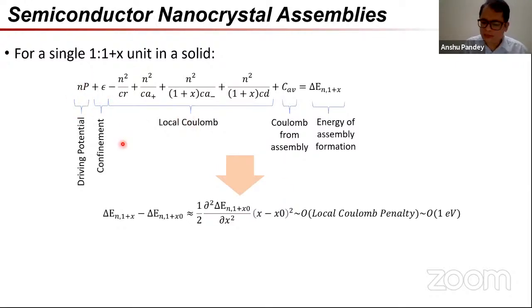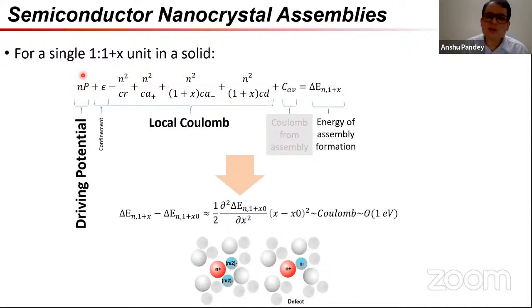And this seems to be fitting our data reasonably well, whatever we collected over here. We were able to show that the main leading terms which contribute to the energetics of formation of such structures are, firstly, the driving potential, which is how much is the potential difference between the accepting state and the donor state, which are now on two separate nanocrystals. And secondly, whatever are the local Coulomb corrections which operate in the assembly. Now, say we have an AB2 type assembly. This is a very simple, perhaps contrived example, but it does illustrate what's going on.